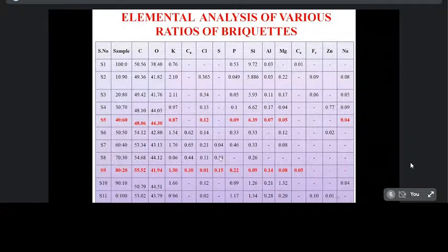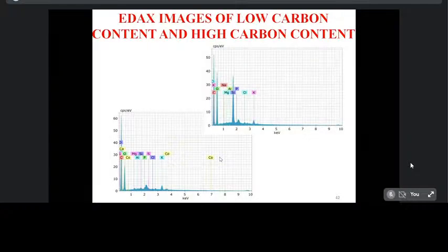So sample S5 has the minimum carbon, that is 48.06%, and sample S9 has the maximum value of carbon, that is 55.52%. The second leading value is oxygen, that is 44.30% for sample S5 and 41.94% for sample S9. The remaining nearly 12 elements fall under acceptable values. So this image shows the EDAX images of the low and high carbon content.